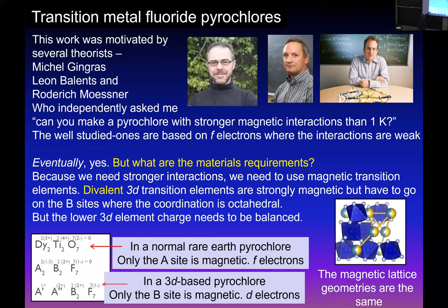This is dysprosium. In order to balance the charge here, if I have to put a d electron ion here, I have to have only 1.5 charges on this site, which means I have to have a mixture of a 1+ and a 2+ atom on that site. I have to put fluorine here instead of oxygen. So this is a little tricky to do. I have to make a fluoride pyrochlore instead of an oxide pyrochlore.